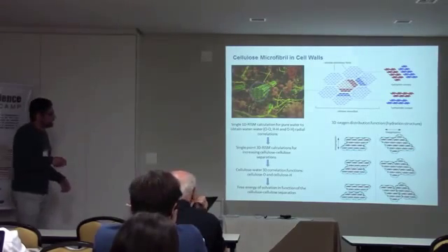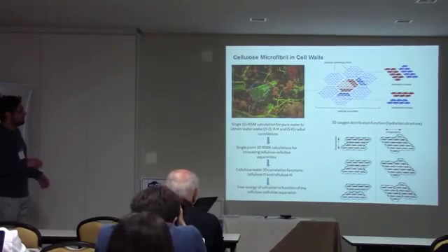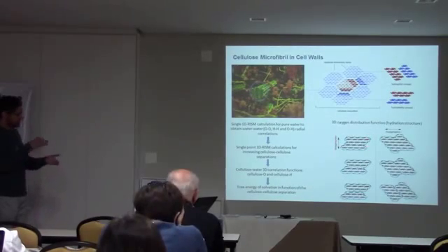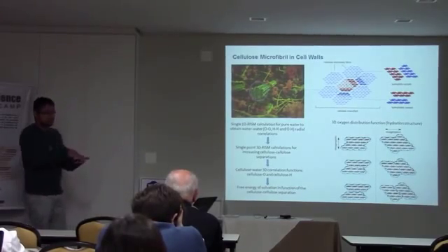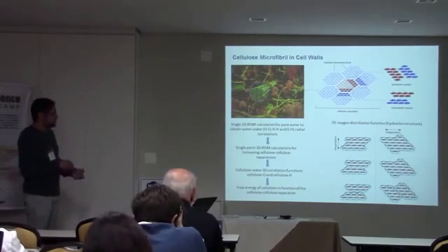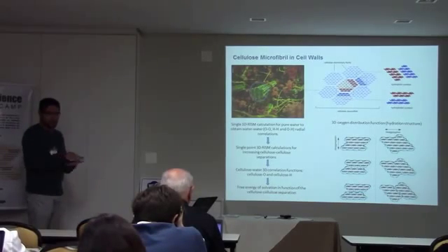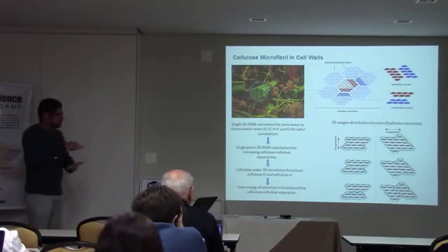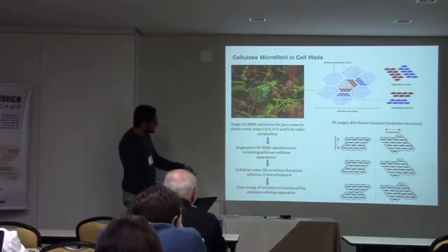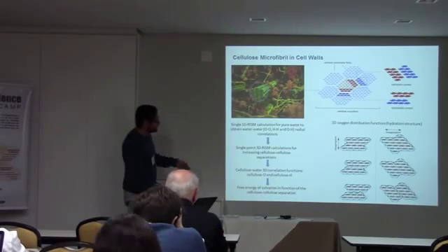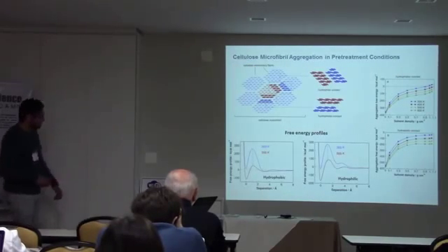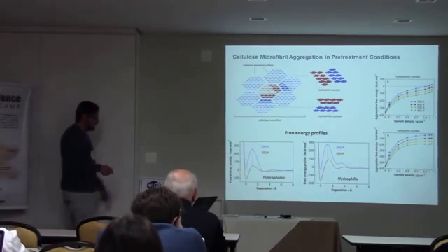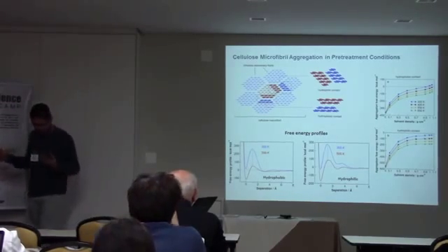So you can see here that in this model of cellulose, when they are packed together, the waters are just around, and then as they move apart, water starts entering in between, and then they create a whole solvation shell when there is no space for water in between the cellulose surfaces. And from that, we can obtain the whole thermodynamics as a function of this arrangement. So this is what we get from that picture before.